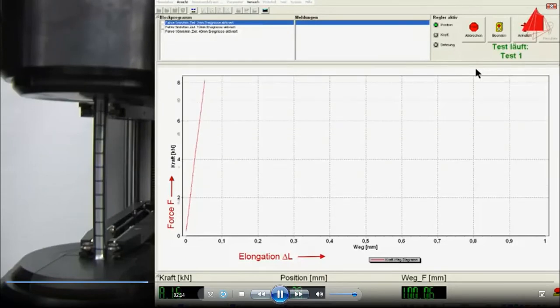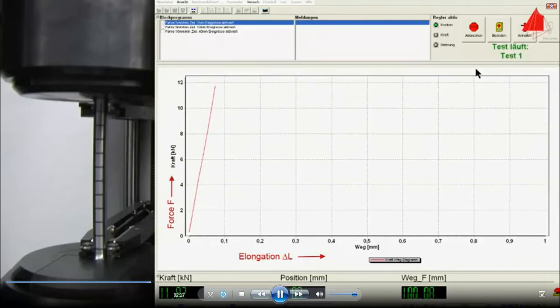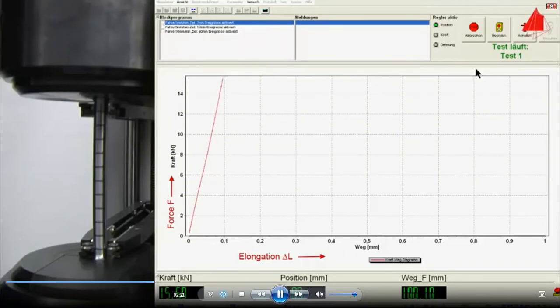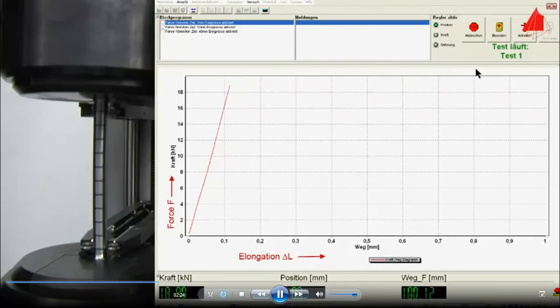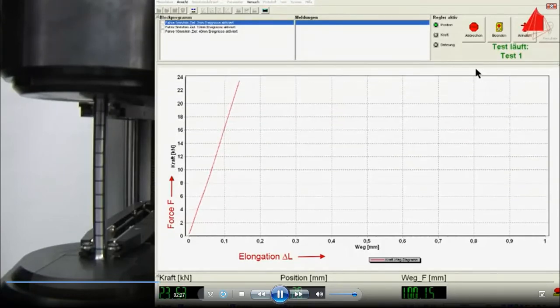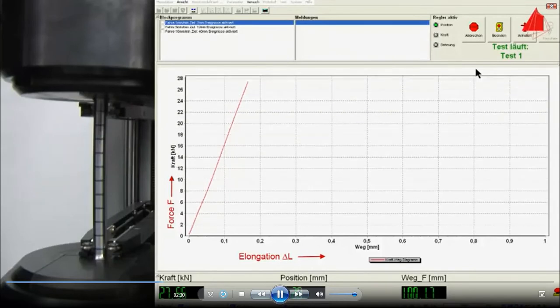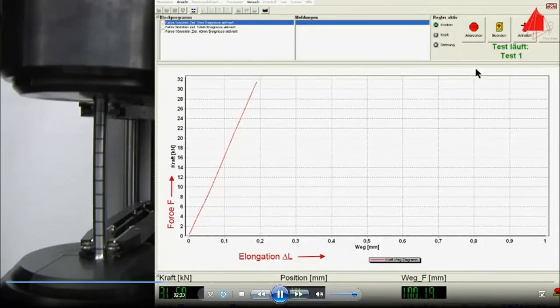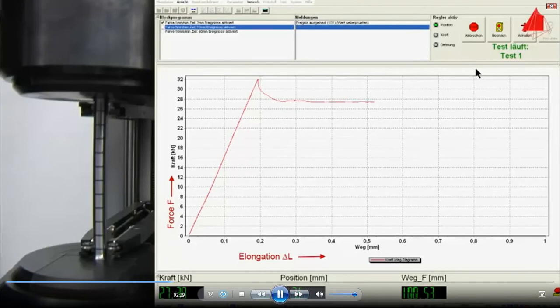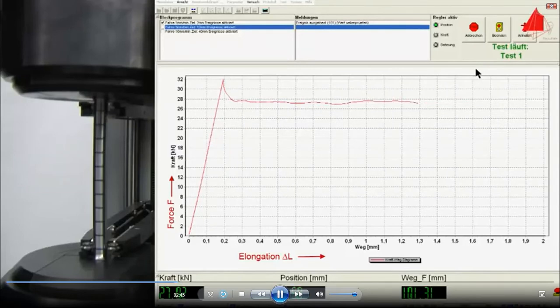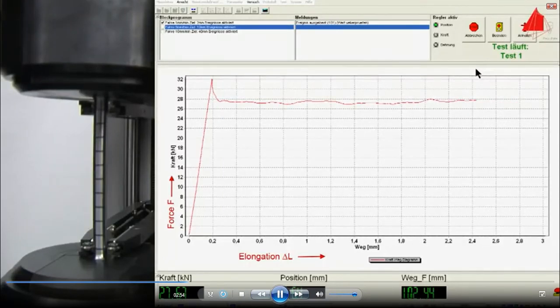Force and elongation are proportional and form a steep, straight line in the diagram. In this area, the material behaves elastically. If the test piece were to be unloaded from this area, it would spring back completely to its original length. In materials with yield point phenomenon, the end of the elastic area can be seen clearly. The plastic deformation starts abruptly and is accompanied by a sudden drop of force. If the test piece were to be unloaded now, it would not spring back to the original length, but instead show a permanent elongation. In the next stage of the tensile test, an almost constant force level with slight fluctuations occurs. This phenomenon is called the Luders effect.